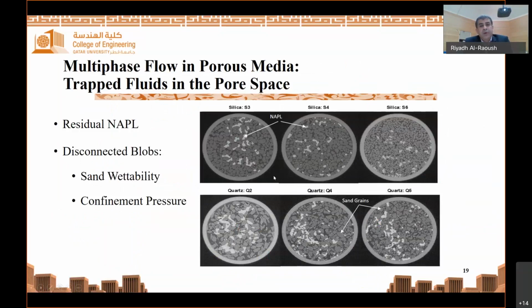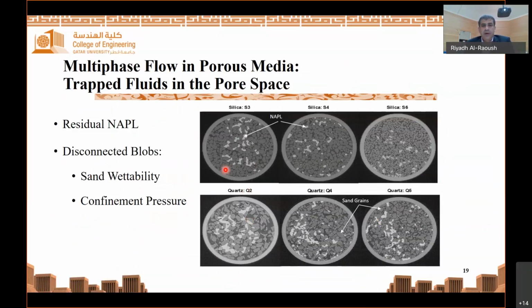This is another environmental application where we use synchrotron microtomography. Here we looked at the distribution of trapped fluid in different geometries of the porous media. From 3D images, we can obtain complete and accurate characterization of the trapped fluid as a function of the pore space. The inside diameter of this column is about 1 centimeter, and this data is very useful for applications such as enhanced oil recovery, remediation of contaminated groundwater, and so on. You can see that the gray here is the solid, and the white here is the oil phase.